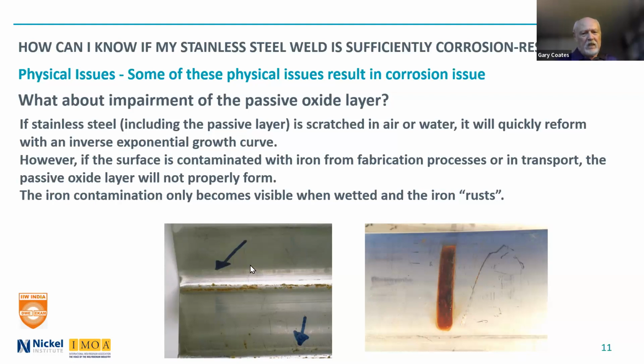The piece on the left there is from a forming operation. It got iron contamination from that. The one on the right is from a strapping material used to hold down pipe, and it was rubbing against the stainless steel pipe as it was being transported, left a mark on there, which wasn't visible again till it was left outdoors and in the humidity and started to rust. So there are corrosion consequences as well as aesthetic ones.